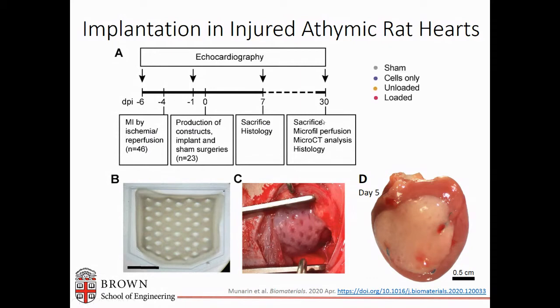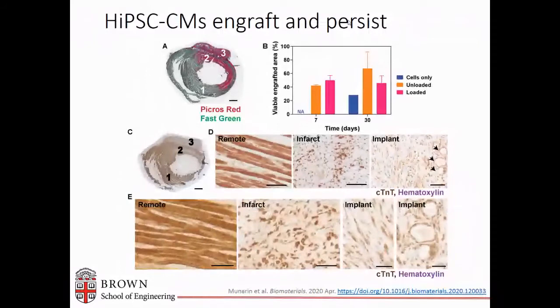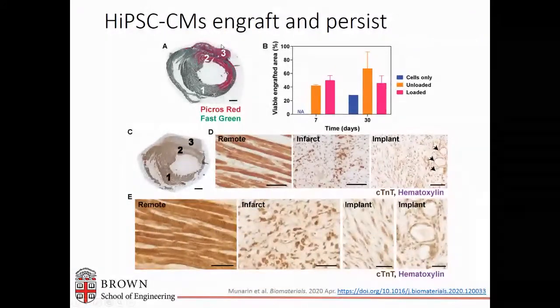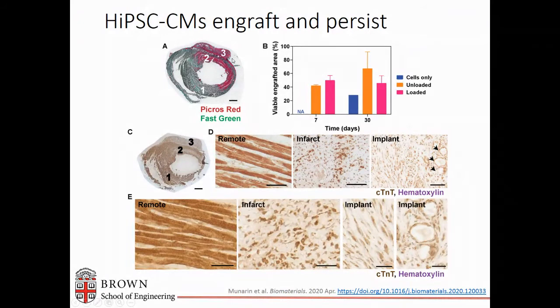And what we had was we had sham groups that had no implant, an implant with only cells, an implant with the microspheres, but no growth factors. So that was an unloaded group. And then the loaded microspheres with all three growth factors in the engineered tissues. So what we found was that the cardiomyocytes were robustly engrafted on the epicardial surface. And at 7 days and at 30 days, the grafts were consistent in size. There was no statistical difference. And we could find in the implant at early and later time points, some nice elongating cardiomyocytes.